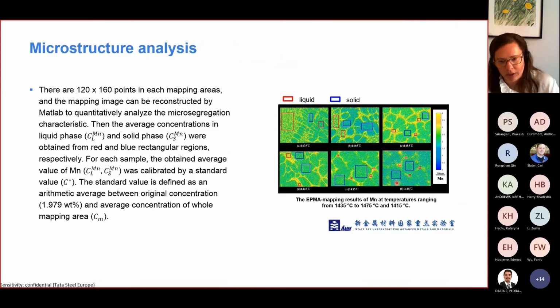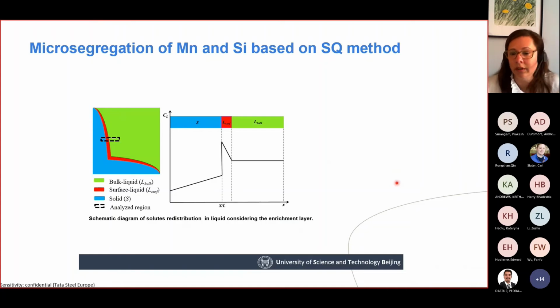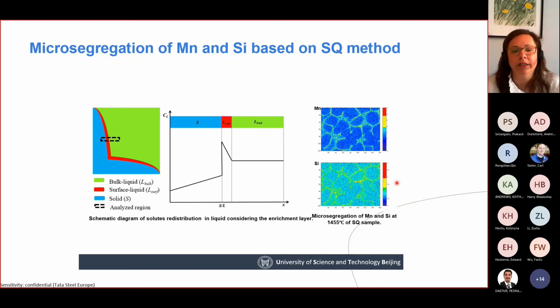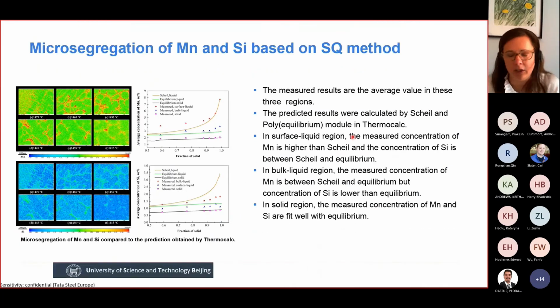If we combine that, and we use again the same samples, and we go to an EPMA and map it, and then we try to understand the segregation of the different elements, in this case manganese and silicon, we could get even more information. Knowing, for example, for a simplified phase field approach, that there is an interface in between the solid and the liquid. That interface, also for phase field, is a very important concept, it could have a different segregation. So if we follow these two, manganese and silicon, excuse me,